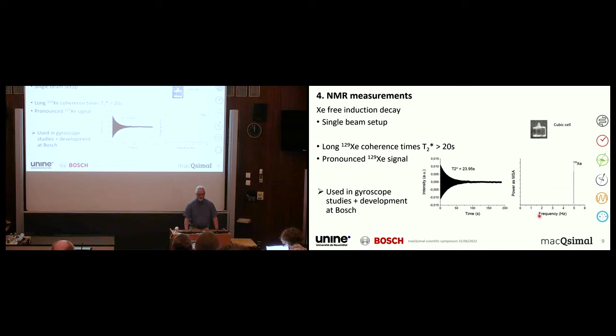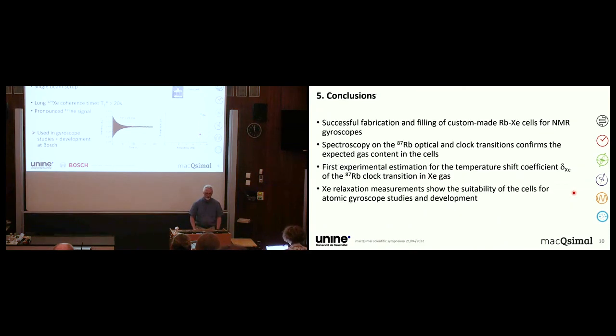And if we then do a Fourier transform of these ring downs, we can extract the frequency of that signal. At this applied magnetic field, we get a very, very clear xenon-129 signal, and it is the shift of this frequency that will later be used to detect the rotation of the gyroscope. And this was done by the development steps at Bosch.